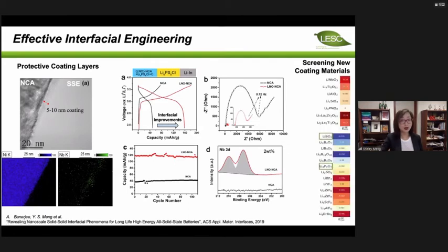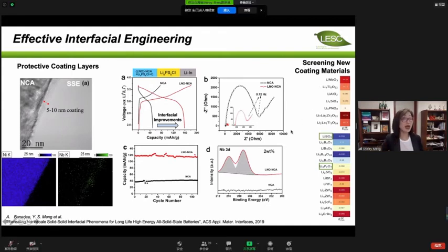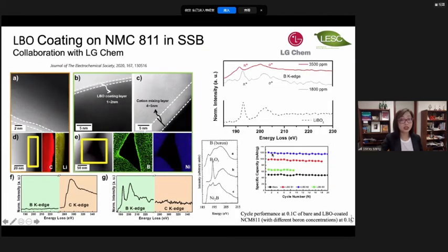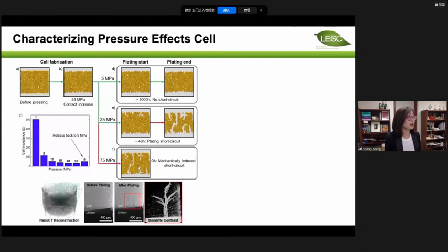In fact, my colleague, Professor Shirley Meng, gave us a list of candidates we can try for computation. We can actually compute what's compatible and what's not compatible. So indeed, the blue ones are very good. We found that the lithium borates are very compatible, and you can produce similar results as the lithium niobates. Now, the unresolved issue is really the mechanical. This is the data we released with LG Energy Solution, showing that the boron coating can enable us to cycle the solid state batteries very, very stably. So mechanical strength is the unresolved challenge.